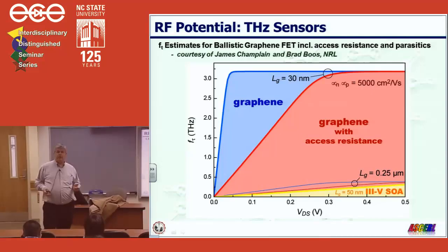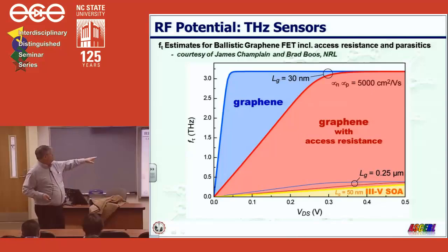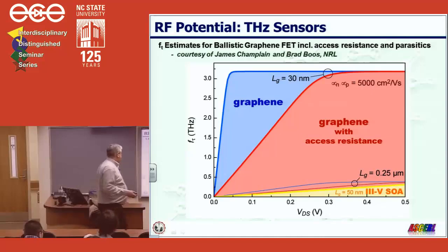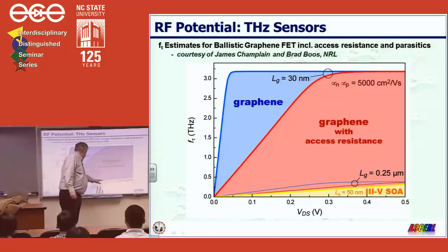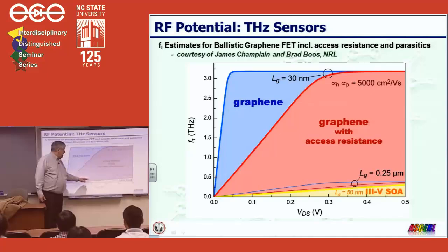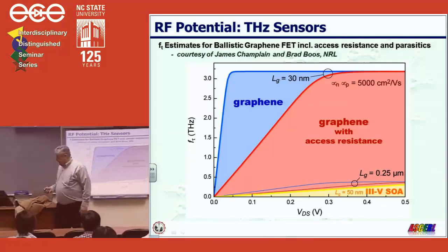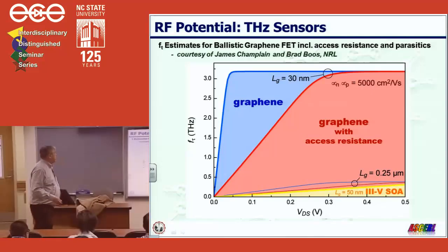We're talking several terahertz. This is data calculated by James Champlain, and it's based upon realistic values taken from FETs that have been manufactured at NRL and HRL, just assuming gate lengths on the order of 30 nanometers. And you can see it's an extremely fast material. And this bottom curve here is the state-of-the-art for the fastest III-V semiconductors, which are all based upon indium phosphide technology. And you can see that for very low drain source voltages, it exceeds the state-of-the-art by easily an order of magnitude. So that becomes extremely attractive.